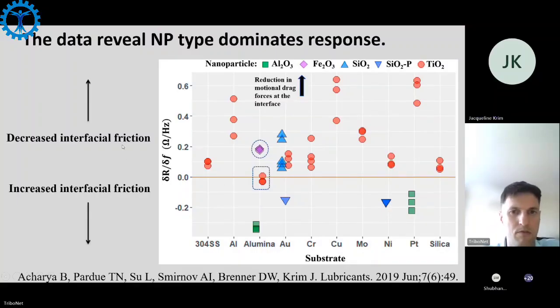Those two circles in the middle, the dashed circles, represent spot checks where we went back in and tried it out on the macroscale MTM. Notice that's alumina, so that's something that the company sells for alumina contacts. And we did see the rank ordering the same. It's not like we saw an exact prediction of what the friction would be, but we did see the rank order. If it increased the quality factor in the QCM when added, it would decrease the friction on the MTM, or at least not increase it as much.